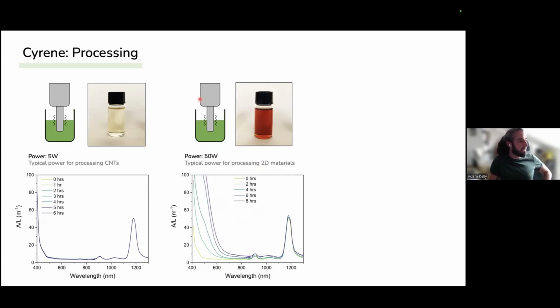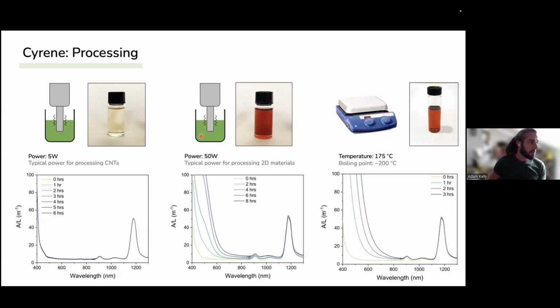Now, the sonication process is quite mechanically aggressive. It's energy intensive. So this is always cooled with an ice bath or with some sort of coolant system. So we did that this time. We weren't sure that it was the heat that was causing it because in theory the solvent should have been cold. So we took a hot plate and an oil bath, and we just heated the Cyrene itself at 175 degrees, because this is now below the boiling point of 200. And what we see is the same changes in the spectra occurring just by heating. So what's happening during probe sonication is that the localized heating of the Cyrene around the side of the tip is causing it to degrade into something in here.